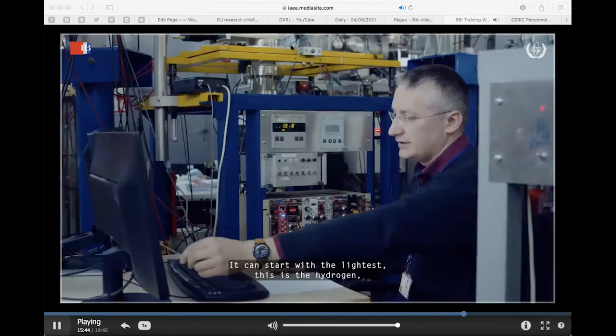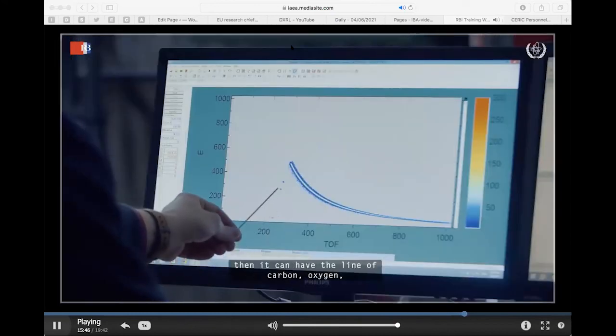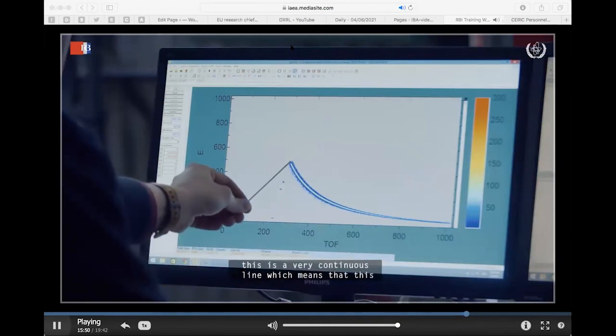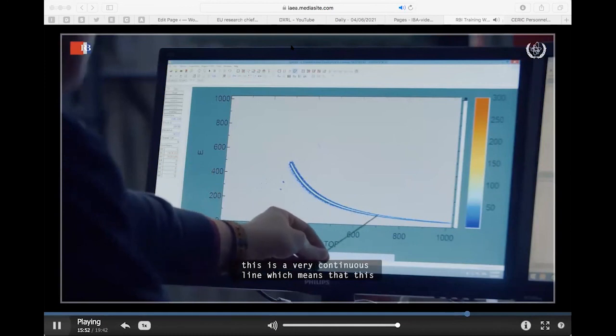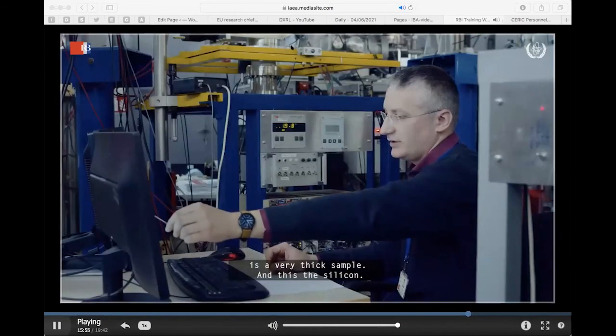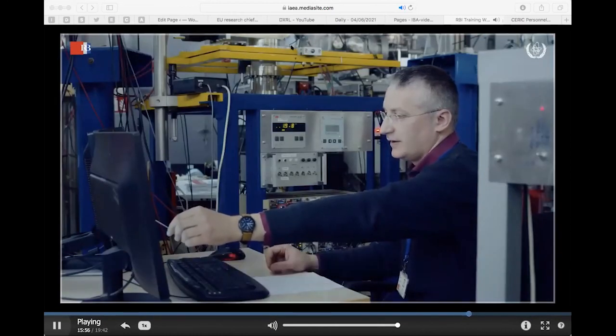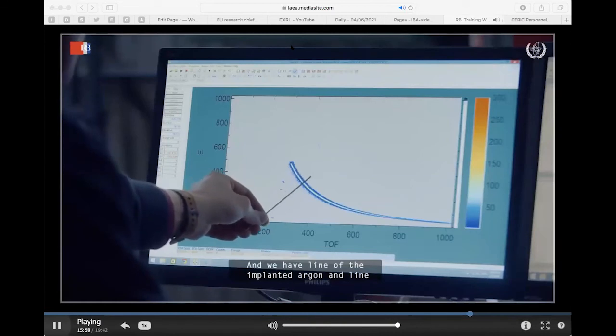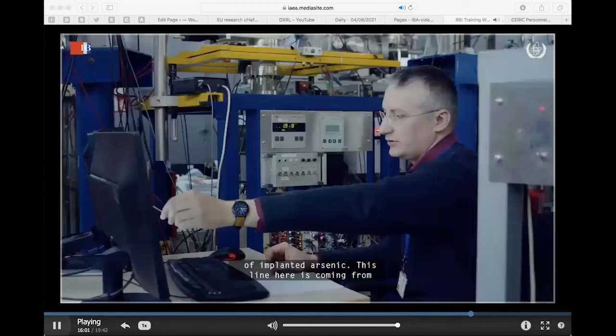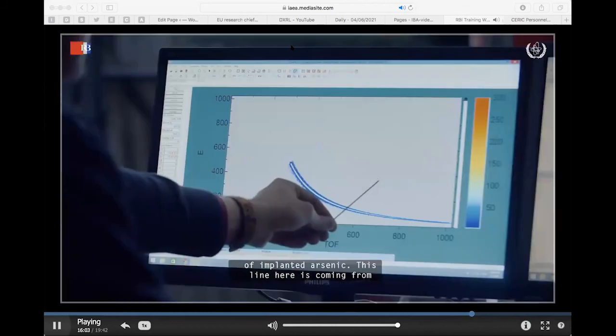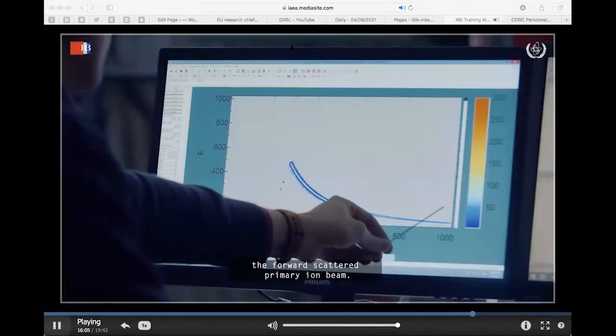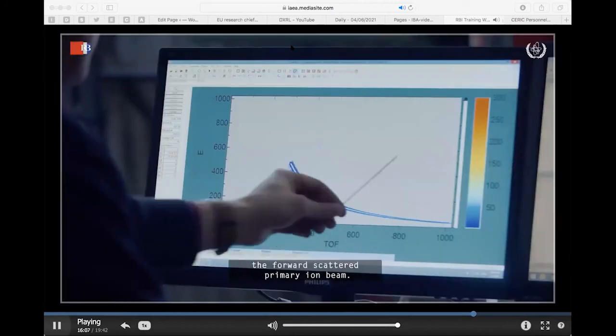We can start with the lightest, this is the hydrogen, then we have the line of carbon, oxygen, this is a very continuous line, which means that this is a very thick sample, and this is the silicon, and we have the line of implanted argon and the line of implanted arsenic. This line here is coming from the forward scattered primary ion beam.